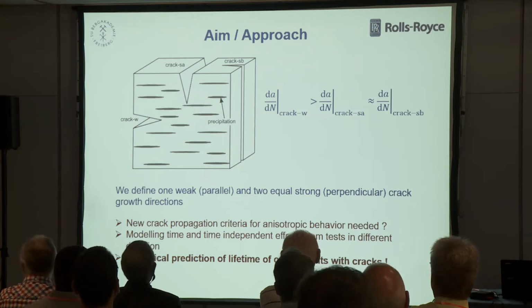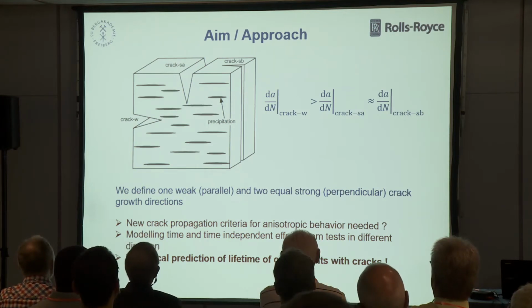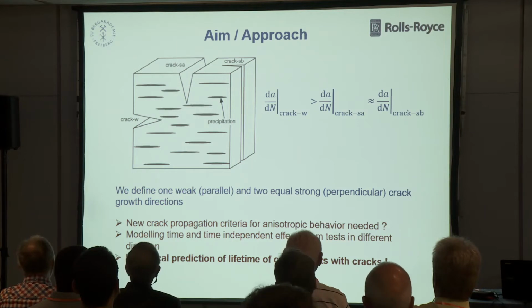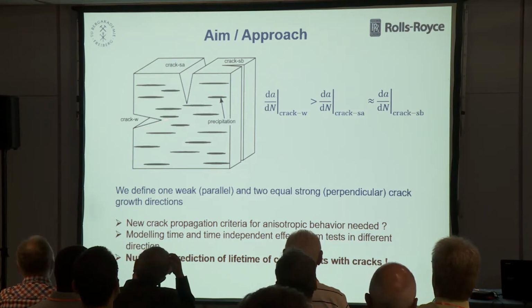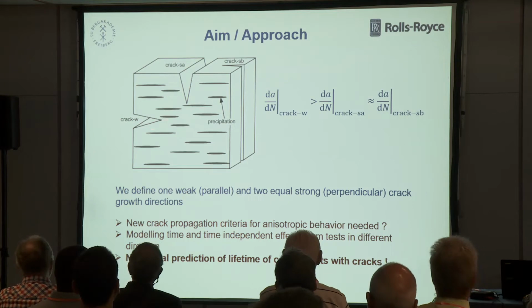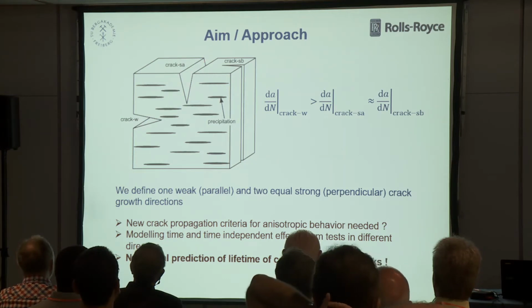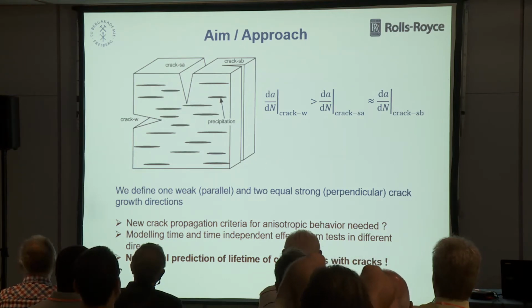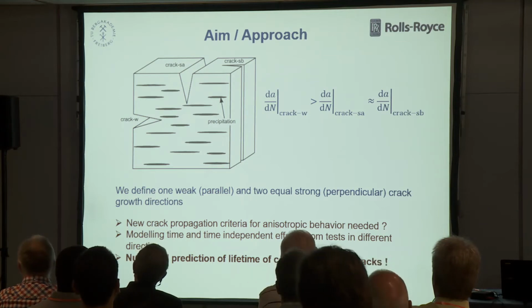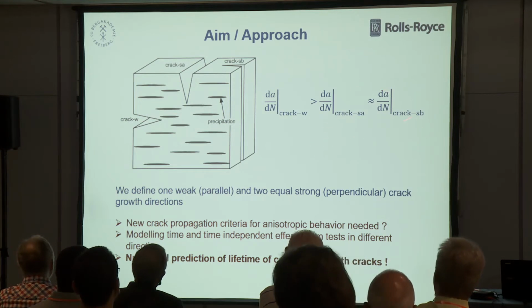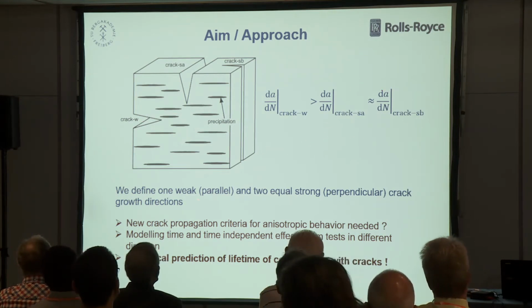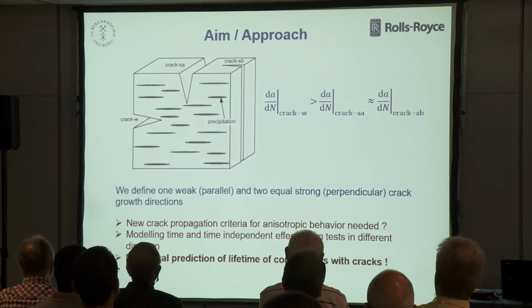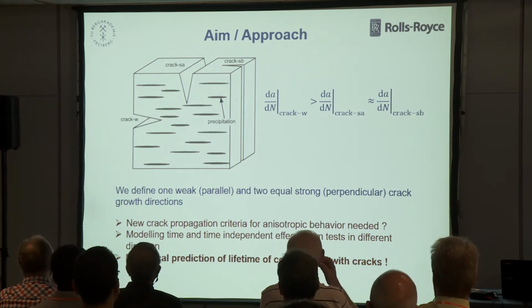So here, this schematic sketch shows maybe more insight. This is a so-called weak direction, parallel to the precipitations. The crack growth rate is great compared to the other directions, here where the crack has to intersect these hard delta phases. And these are about the same, so we can define one weak direction and 2 strong directions, perpendicular.